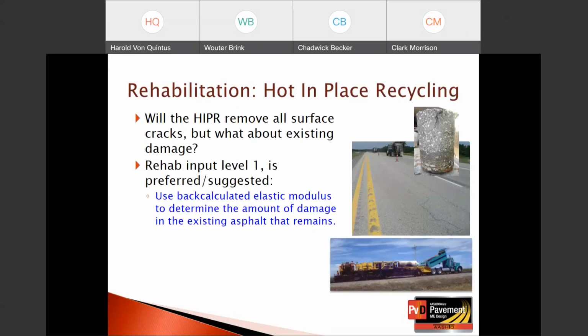Okay, now let's move to hot in place recycling. This is an option that's used, and the question is, will the hot in place recycling remove all surface cracks, but what about the existing damage? Rehab level 1 is what's preferred or suggested, as noted previously, because we'll use back calculated elastic modulus to determine the amount of damage in the existing asphalt that remains, and or our assumption that the cracking we see at the surface, if we do not have cores, then we assume all of those cracks have propagated from the bottom to the surface.